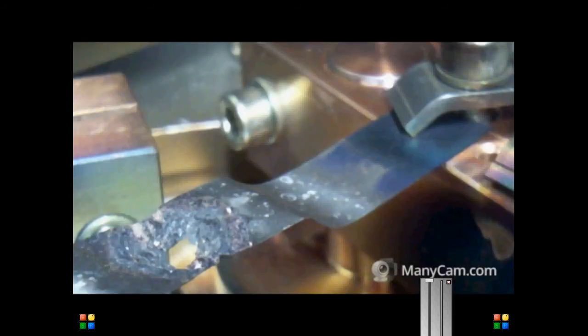Small pieces of copper on the surface of the tungsten. Zoom in, come on. Oh, there it is in the center. There it is, zoomed in. And now we're going to move to the copper at the bottom. One, two, three. This is the drop that you saw melting through the tungsten boat and dripping on the floor of the chamber. Here it is, molten metallic copper formed from copper oxide.